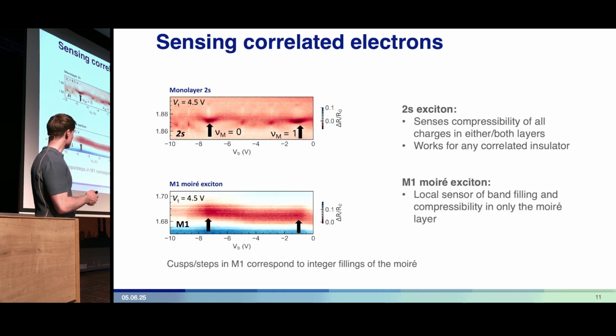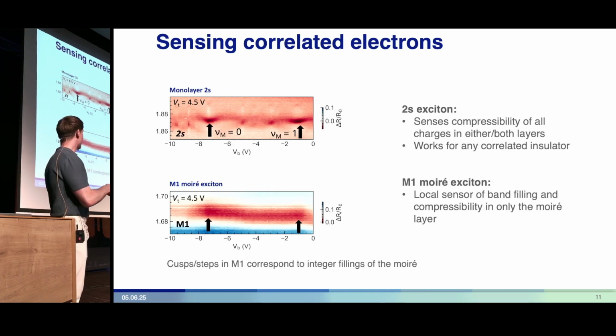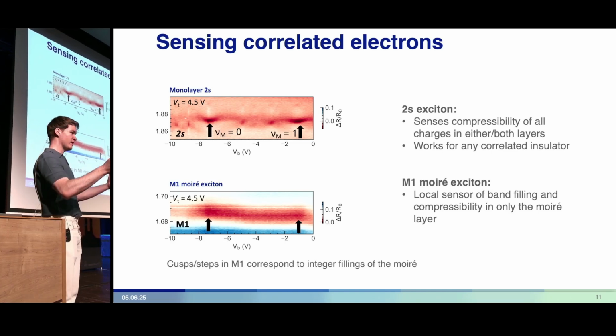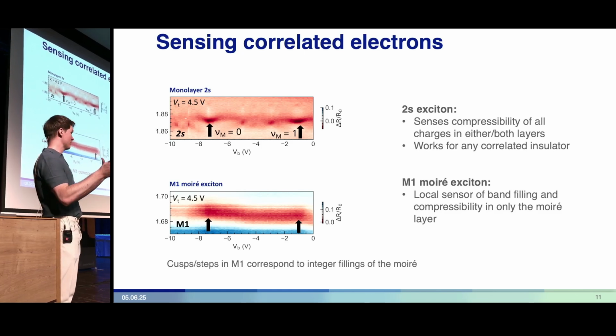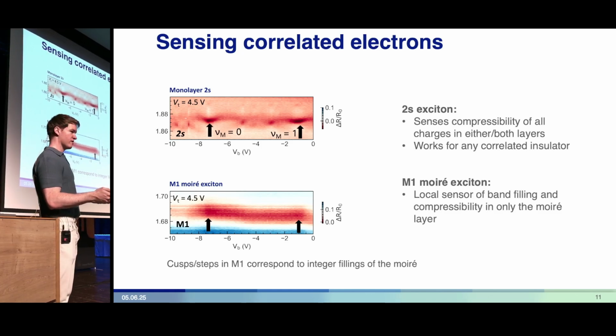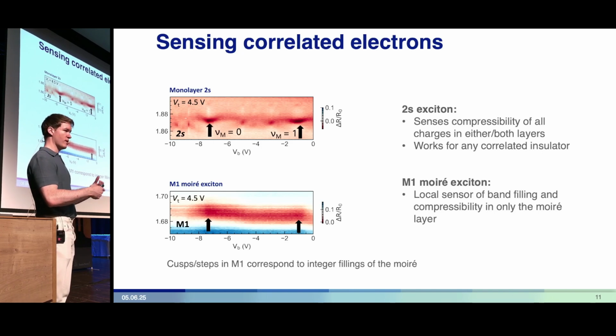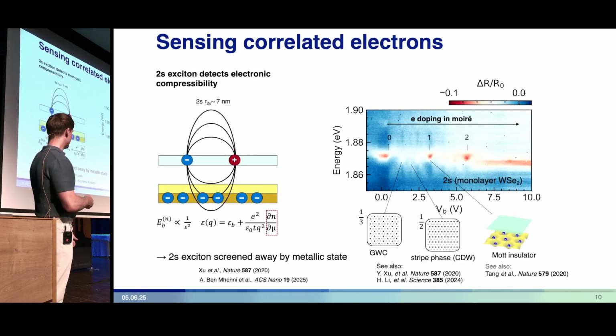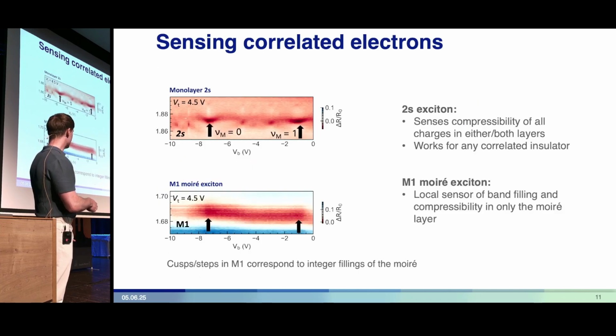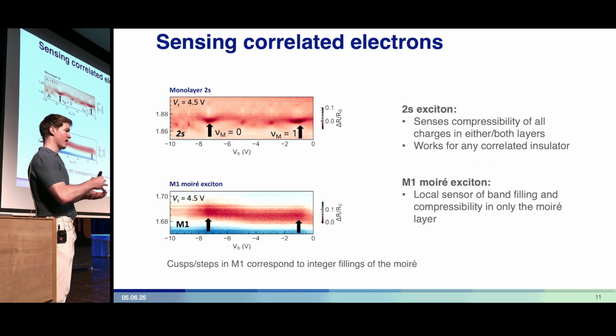So to summarize what these two excitons tell us: the 2s exciton senses compressibility of all the electrons in the system, and it works for any correlated insulator, whether it's a generalized Wigner crystal, a Mott insulator, or a band insulator. The M1 Moiré exciton is a local sensor of band filling. It detects whether you've filled a Hubbard band in the Moiré layer. It doesn't really care about electrons which might live in the nearby monolayer.